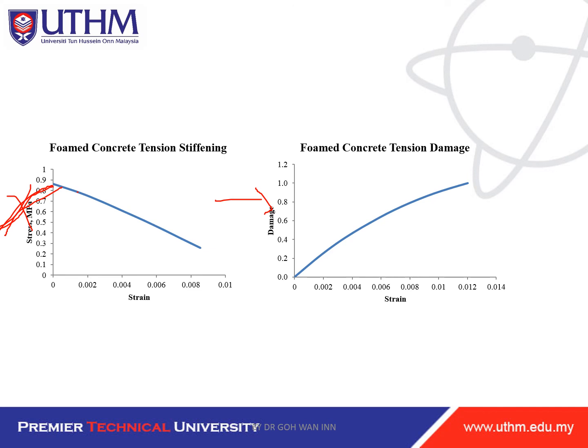The data from both compression stiffness, compression damage, tension stiffness, and tension damage graphs are all inserted into Abaqus. As a reminder: for the tension damage, do not put zero as the last damage value — if you input damage as zero, it will cause errors during simulation. I will explain this further when I show the Abaqus simulation. Thank you, bye!